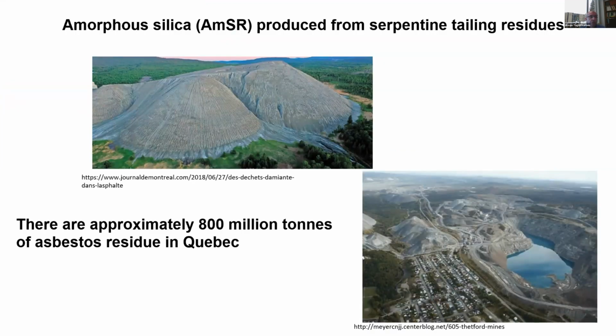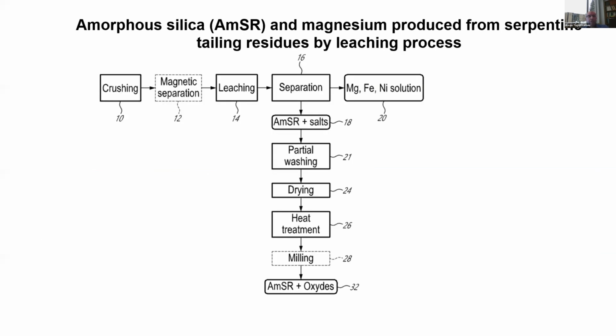One is close to Sherbrooke, and you all heard about the million tons of the asbestos when the quarry was closed. We end up with mountains of those materials, and now there are some companies who are doing a great job by treatment of the residues, by extracting from the serpentine the magnesium. But when they extract the magnesium, they end up with amorphous residue. So they are doing a sort of leaching process. This is the separation. They produce magnesium and other oxides, but also they produce silica-rich amorphous.